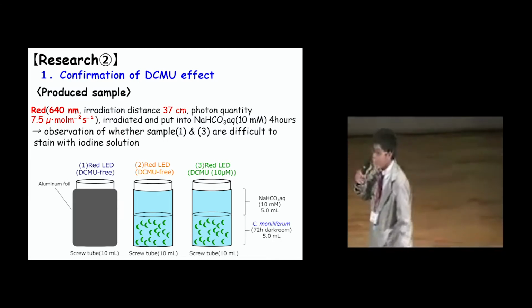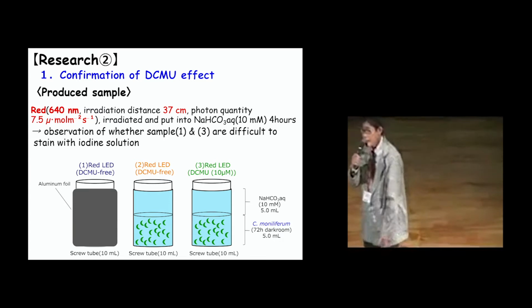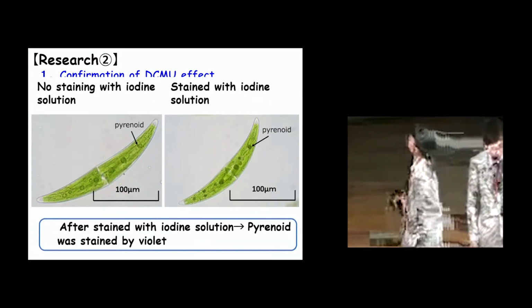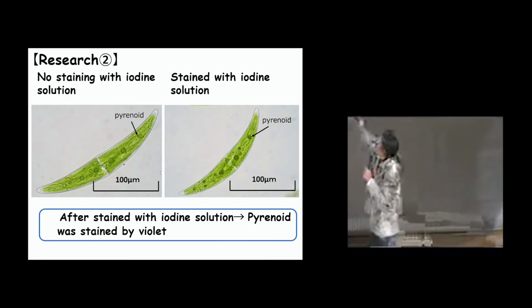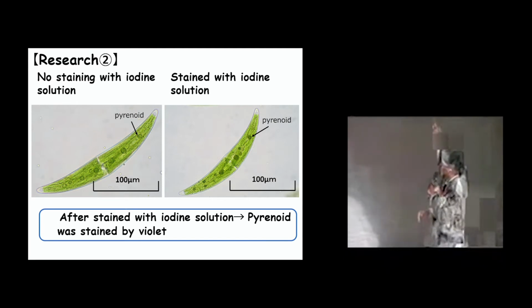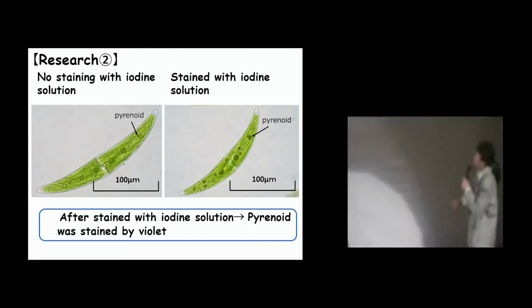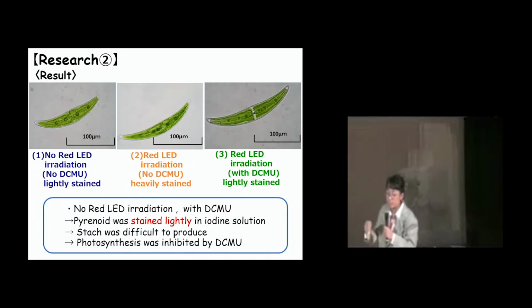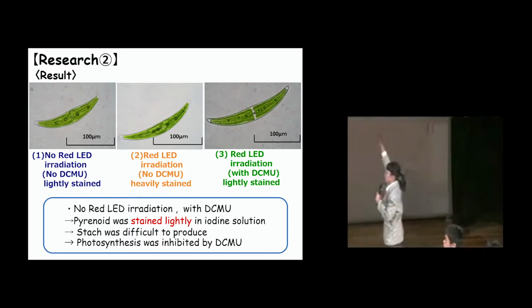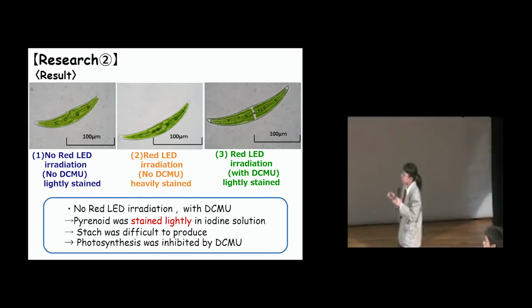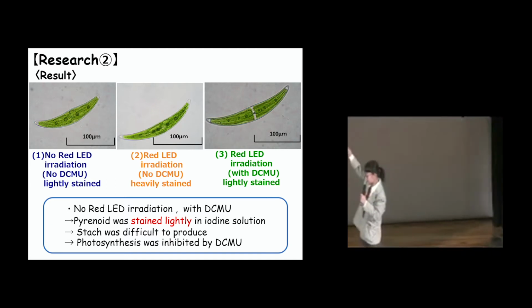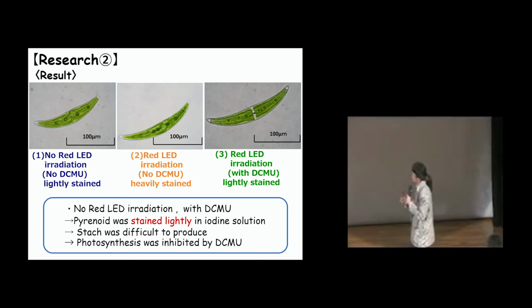Observation of whether samples 1 and 3 are different with iodine solution. After staining with iodine solution, pyrenoid was stained violet. As a result, the pyrenoid of the sample with DCMU, which did not irradiate red LED, was difficult to stain with iodine solution. I thought that was because it had to be made from cells which photosynthesized. Therefore, it can be said that photosynthesis was inhibited by DCMU.